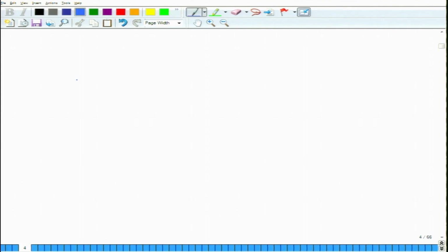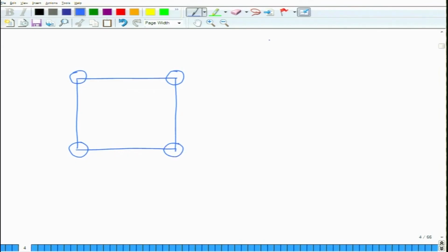So the way this structure works out is in this fashion. Remember the coordination numbers: calcium coordination number is 8 and fluorine coordination number is 4. So fluorine is tetrahedrally coordinated, and calcium is cubic. Let us just draw a top view of the lattice here.